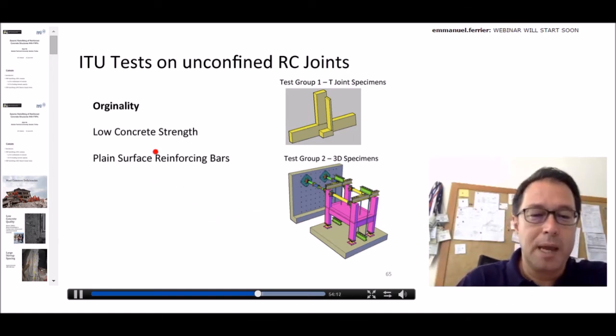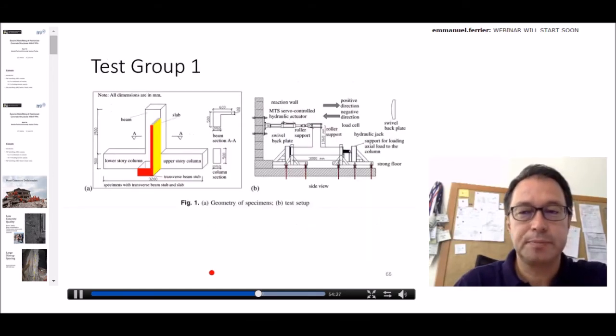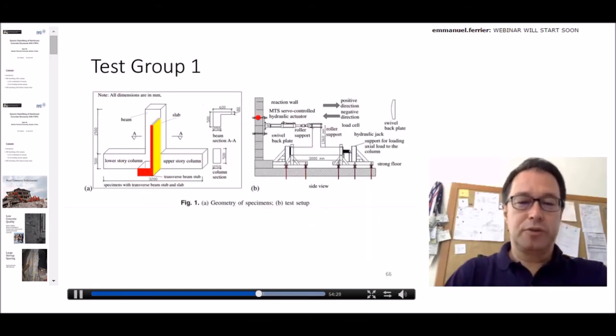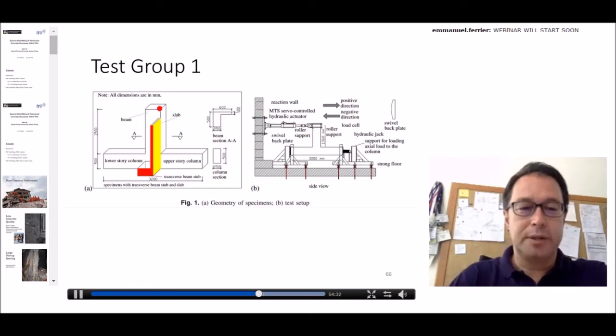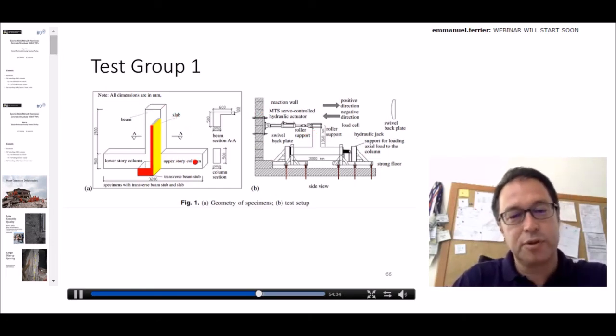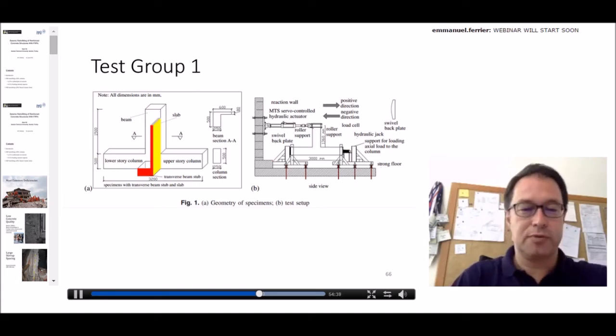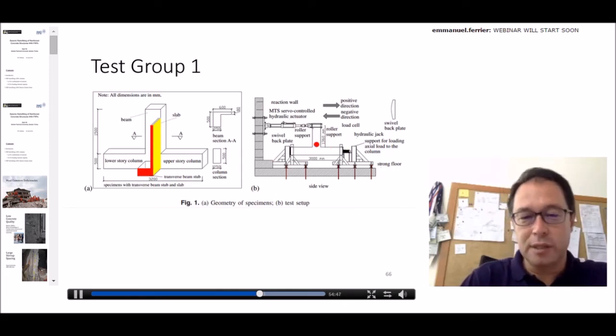Again, the original specimens, or reference specimens or pilot specimens, have certain deficiencies, like low-strength concrete, as well as usage of plain surface reinforcing bars. So this shows the test setup of group 1 specimens. This is the column of the upper story. This is the column of the lower story, the beam, slab, and transverse beam. As you see here, we test the specimen in the horizontal direction, which means that the columns are horizontal now and the beam is vertical.